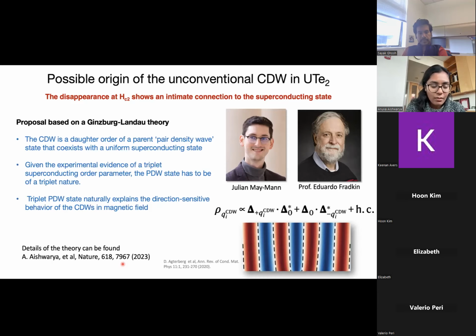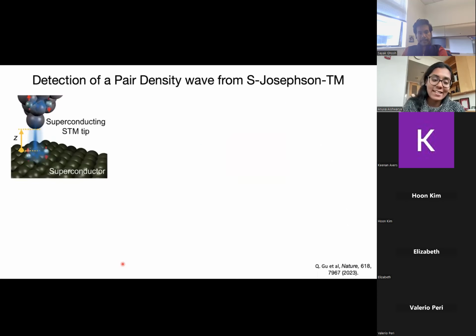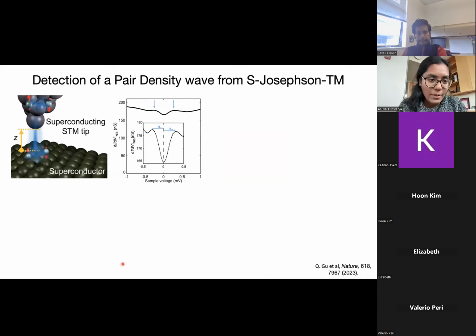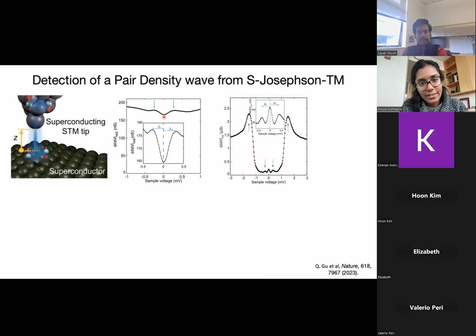So what is nice is that subsequent experiments from Professor Seamus Davis's group using Josephson STM has actually detected these pair density waves. So in this experiment, they take a superconducting tip and look at a superconductor. And for them, the tip is made of niobium. So this is data from a normal tip where we see an extremely shallow gap. But when you look at it with a niobium tip, you can move the gap by delta 1 plus delta 2, and that's what this is.